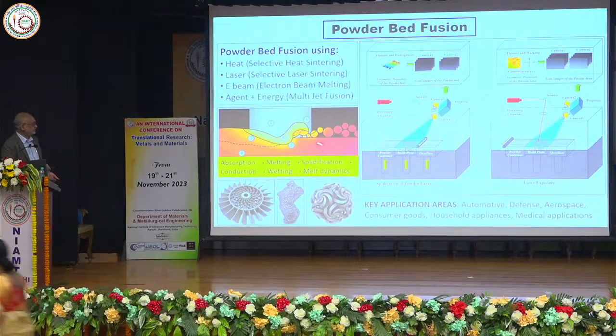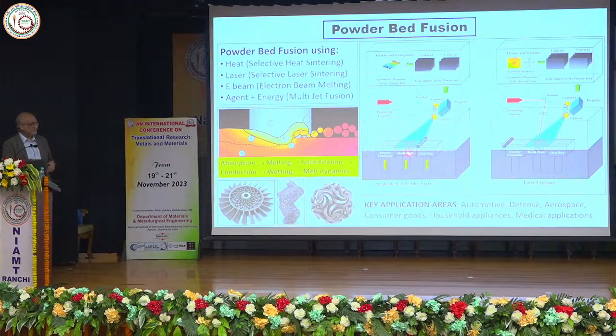So I have a bed of powder, and I have a source of heat, and let's say that source of heat is actually a very small line or a spot, and the moment it moves over or hits a point, I immediately melt and fuse, and then I move the beam. So obviously, by the time the beam is moved out, the previous point is already solidified. So likewise, I'll have droplets, or essentially small volumes of fusion regions, moving linearly in one direction, then in the perpendicular direction, and when I complete this entire X and Y over a given area, then I have a sheet, and when I start building vertically, then I have a three-dimensional component.